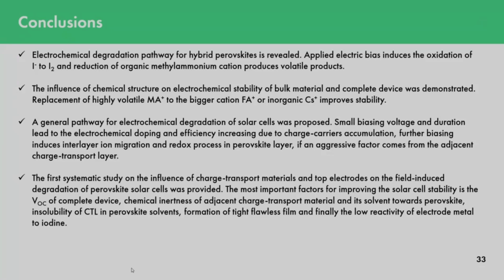The influence of chemical composition on the electrochemical stability of the bulk material and the complete device was demonstrated. And we concluded that replacement of highly volatile methylammonium with a bigger cation like formamidinium, or even inorganic cations like cesium or rubidium, improves the stability of the device. And actually, addition of some excess of lead iodide, which is one of the products of degradation, could also lead to some positive changes.